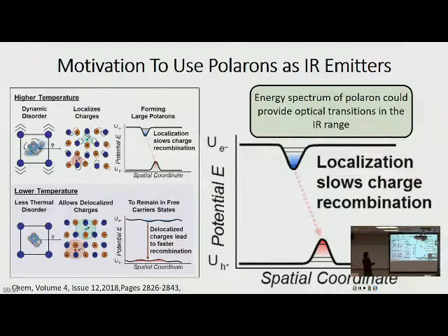You can see here, you put an electron here, it pushes the negative charges away, and it draws positive ones towards it. And then vice versa, if it was a hole, it would do the opposite. That's basically the idea behind a polaron. What that does is it stabilizes that particle and makes it more robust. That's probably a bad word, it's not very physical. Basically, you get charges that localize in space, and then they become resistant against scattering off phonons in the lattice. So they have extended lifetimes, and it slows down charge carrier recombination too.